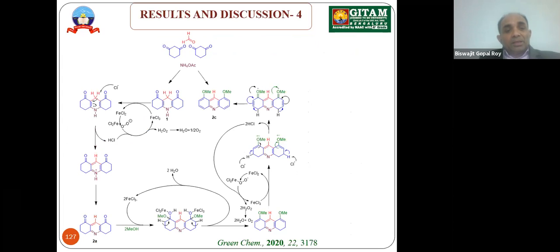Next slide, please. So from all the controlled reactions and whatever yield we got in the different stages of the reaction, we have proposed this mechanism. First is the formation of this one, that is reported already, as I told. But next is this one. This one happens with the attack of methanol in presence of FeCl3, and this is the rate determining step. We have never found a compound like this, or any compound that got aromatized where the OMe didn't get incorporated. So we can tell that this is the rate determining step. And as it is happening in presence of FeCl3, we thought that FeCl3 is acting as the Lewis acid. And once this happens, after that the aromatization takes place. Next slide, please.